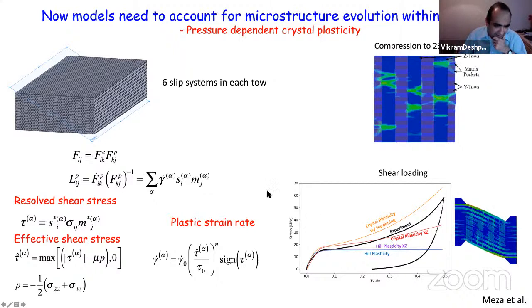You might also say, why did you do all this complicated crystal plasticity? You could have just modeled each toe as a Hill plasticity model with all the anisotropies. And if you do that, that's this line here, Hill plasticity basically does not predict the hardening that you're getting here. And this hardening is because the microstructure within each toe is evolving, which is being captured by the crystal plasticity. If you did Hill plasticity, you just would not capture it. So you need all this complication really to capture what are relatively simple tests.